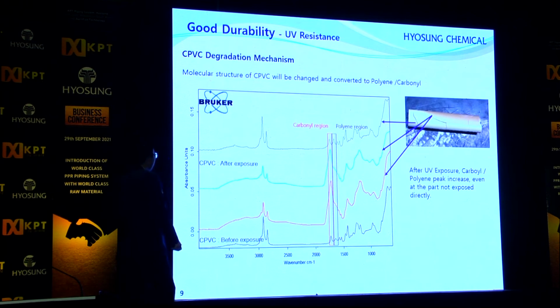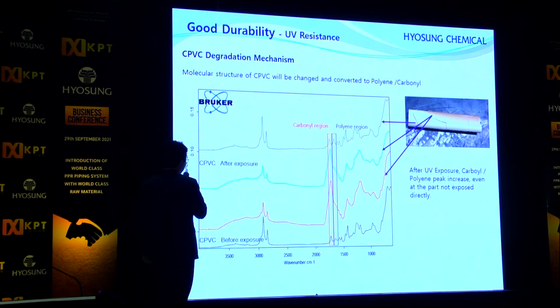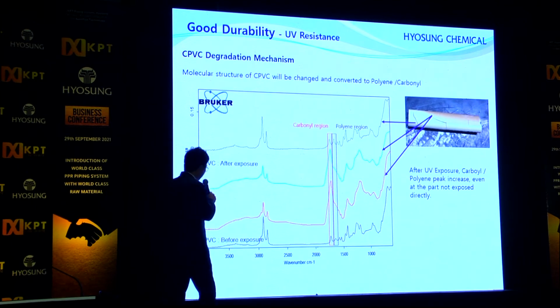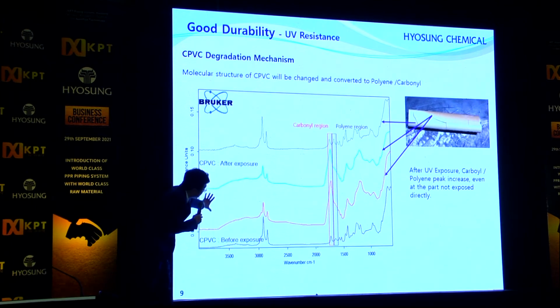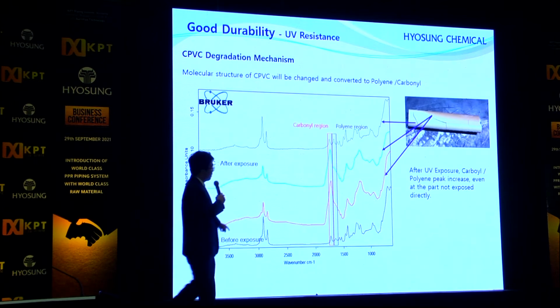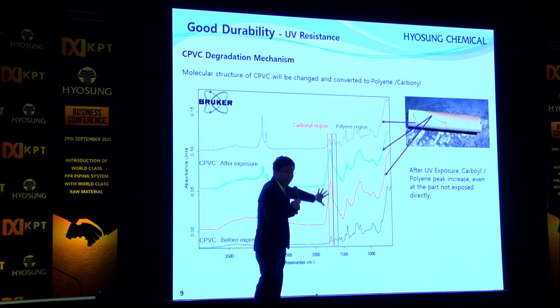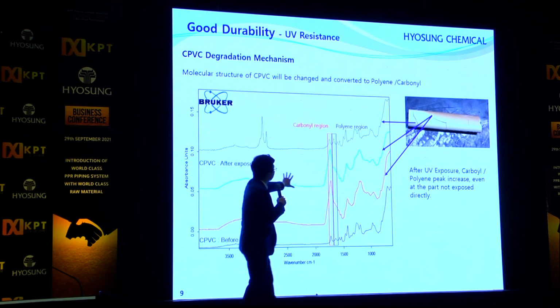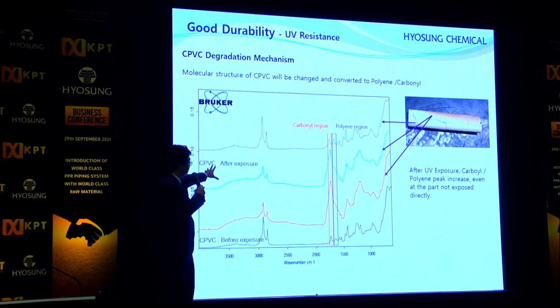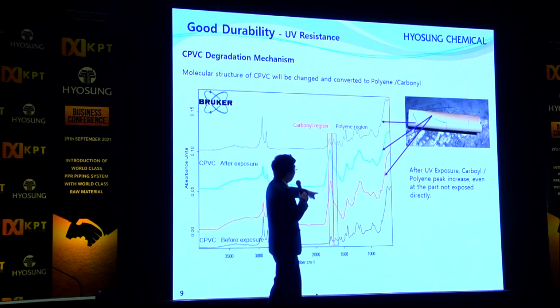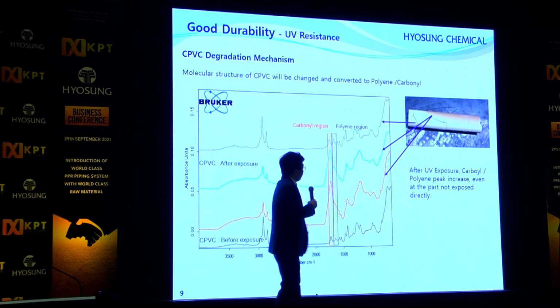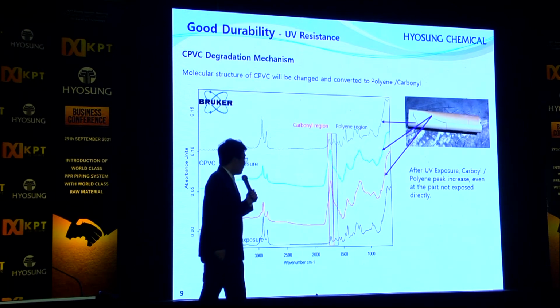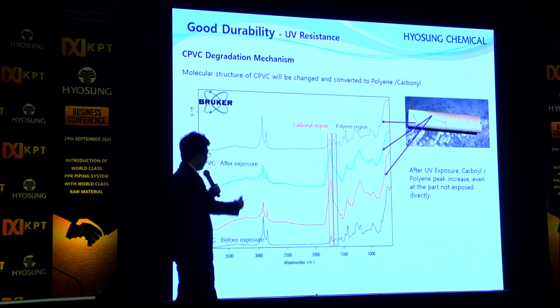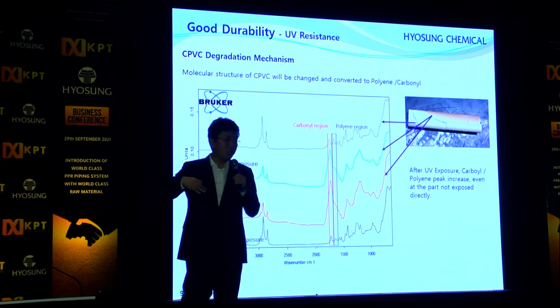This is the chemical change of CPVC after UV exposure. These two lines are before exposure. These two lines are after exposure. You can see the peaks are changed. From the carbonyl region, it is changed to the polyene region. So after UV exposure, the CPVC structure is deformed or changed, we can say.